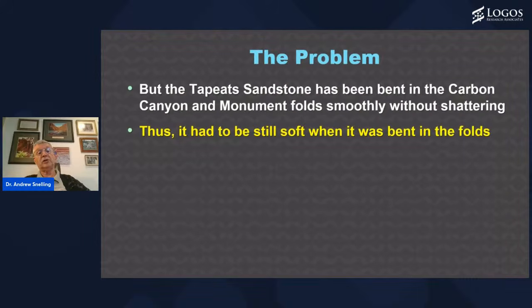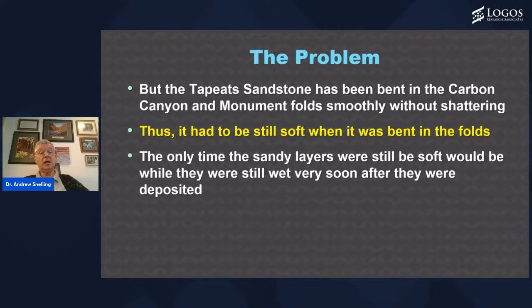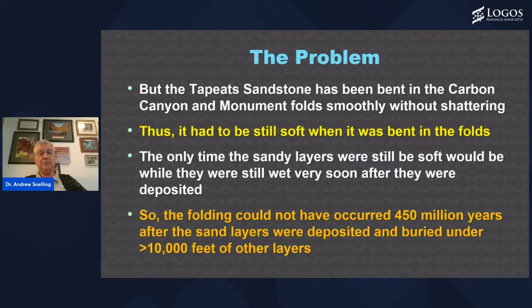Thus, we have to conclude it was still soft when it was bent in the folds. It was still bent and pliable, otherwise it would have shattered. Now, the only time the sandy layers would still be soft would be while they were still uncemented, when they were still wet, very soon after they were deposited. And we'll come to the other possibility in a moment. But when we think about it logically, soon after they were deposited, when they were still wet and moist, the layers would be soft enough to be bent.